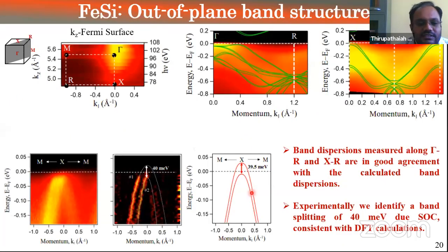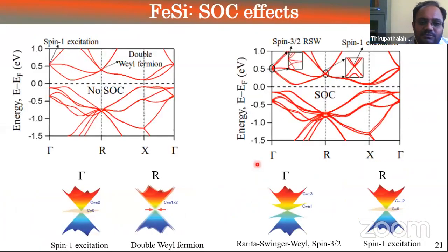Initially, we didn't understand, but later on, we realized that that's how we actually calculated the SOC band structure. After calculating the SOC band structure, we realized that this gap is actually due to SOC splitting, and this gap matches very well with the calculated band structure. And in fact, this has implications. When you have no spin orbit coupling, as predicted earlier, at the gamma point you have a spin 1 excitation, and at the R point you have a double Weyl fermion.